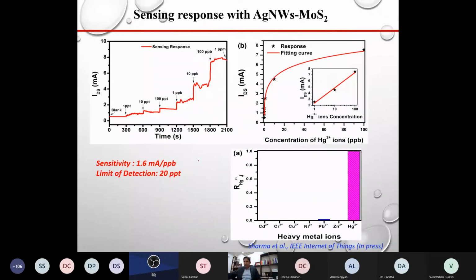We transferred this on the gate, in between source and drain. Then we did the measurement, and we are getting a very good response when we change these concentrations. Here is the selectivity test and the sensitivity. In this case it is around 1.6 milliampere per ppb, and the detection limit is also very low. Here we can see that even ppt can be measured, and at 1 ppb there is a good enough change in milliampere, so we can measure it easily.